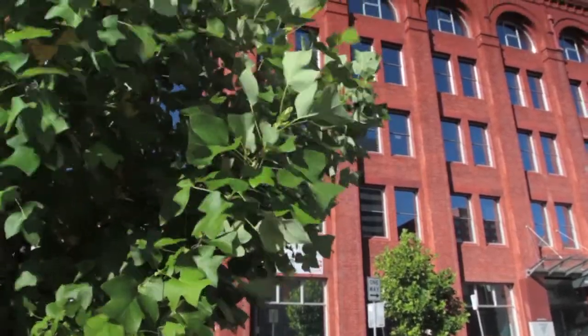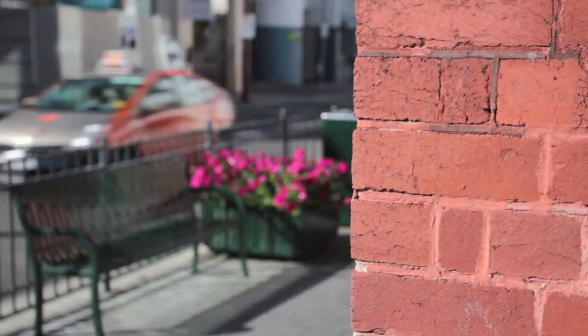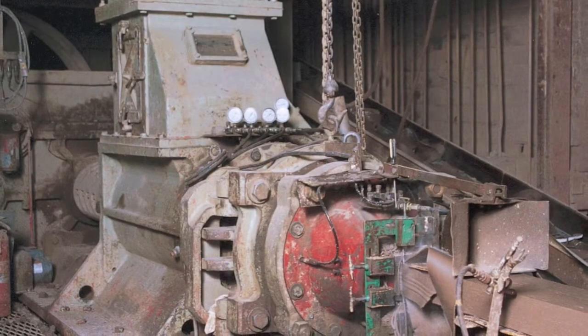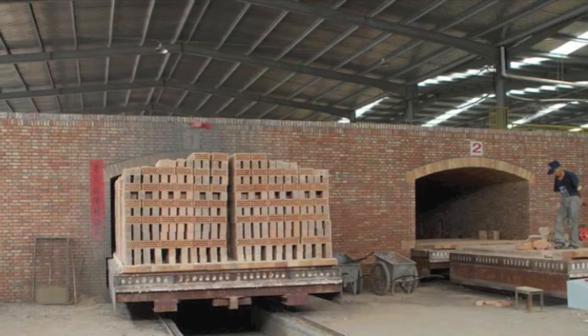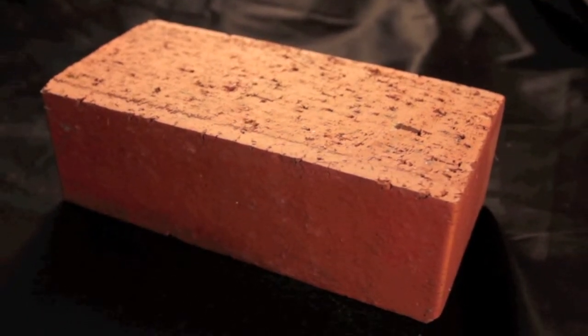Up to 40% of the bricks were of a lower standard. The great step forward came in the 1880s when brick making was mechanised. The clay was worked at a much lower moisture content, the pug was extruded out of the machine and then cut with wire. The bricks were immediately stacked on trolleys which moved slowly through the kiln where temperatures could be finely controlled. This resulted in a quicker process, less handling, and a uniform brick quality. Machine-made bricks are fired at a much higher and more consistent temperature than handmade bricks and are thus a more durable brick.